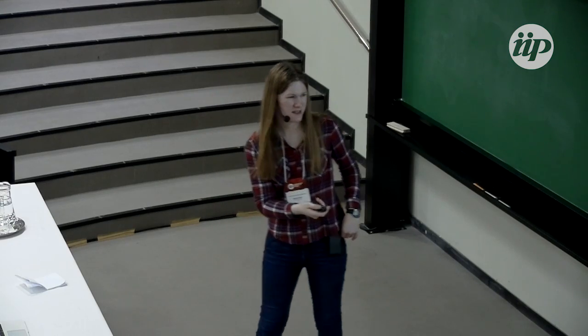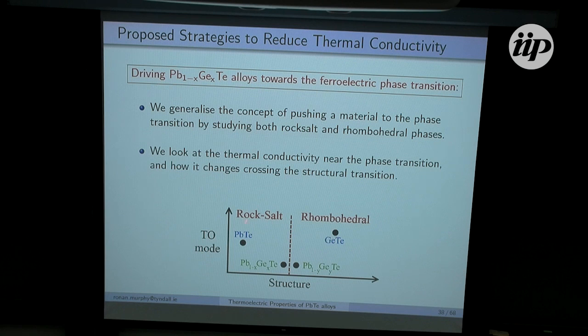So just to demonstrate this, I have a little mock-up here of, say, the TO mode frequency against the structure. You can see in the rock salt phase, you have lead telluride, and then in the rhombohedral phase, you have germanium telluride. And as you vary the alloy composition, you can imagine it gets closer to the phase transition, the TO mode becomes softer, and the phase transition occurs here.